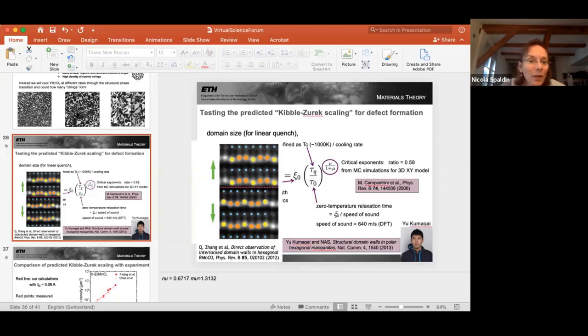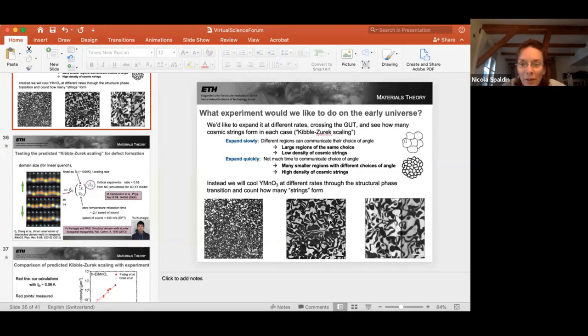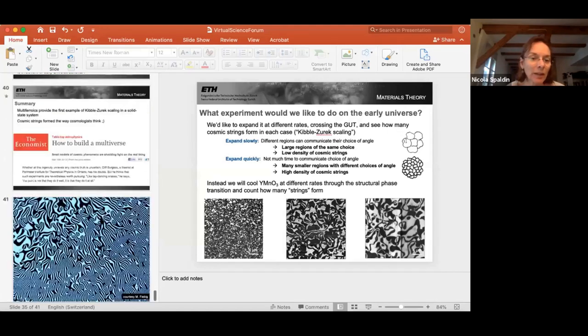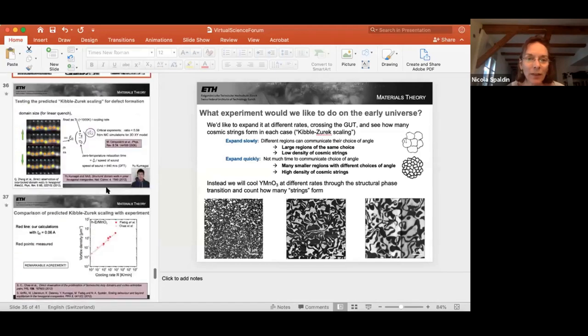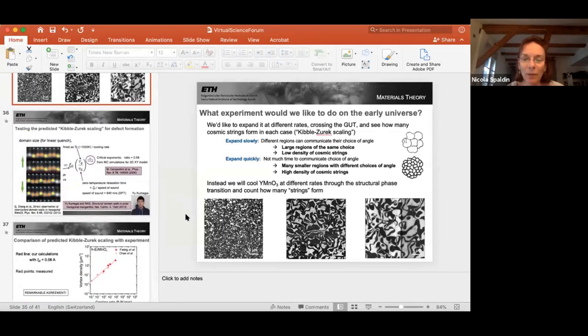Another point to notice, so these images are looking from the top perpendicular to the layers, but when one looks from the side, one sees actually rather similar images. So the anisotropy, and actually the density of vortices from this side is very similar. The anisotropy is much less than we expected. And this is, to me, surprising. It's really surprising. I agree completely that I would have expected it to be much more anisotropic.